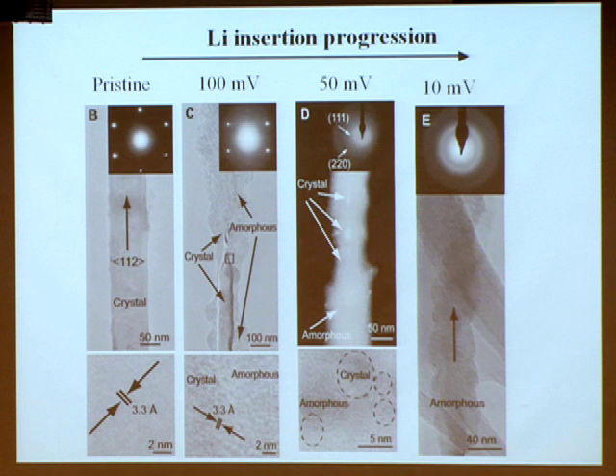And with some lithium coming in, part of the nanowire now becomes amorphous, and part of the nanowire is still single crystalline. So this is amorphous silicon with lithium in it. After you put more and more lithium in, the crystalline nanowire becomes almost completely amorphous, leaving behind this dot. That's a tiny, tiny crystallite of silicon. At the end, these nanowires completely become amorphous after a lot of lithium goes in. Our detailed studies have shown this is really the picture happening. During the first cycle, when you charge lithium into silicon, it goes through this transformation from crystalline to amorphous through these different stages.